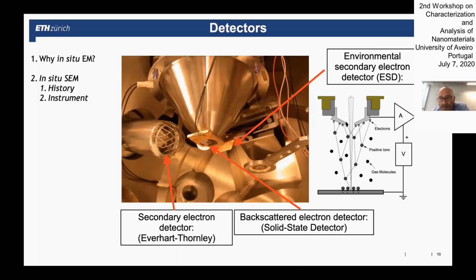And on their way, when they get accelerated towards this anode, they can hit gas molecules that are in the chamber and ionize these gas molecules. And in this process, create more secondary electrons in the gas phase. And they get also accelerated to the positive anode, and eventually even excite more secondary electrons through further interactions with gas molecules. So what you have is that a single secondary electron actually can give rise to an avalanche of secondary electrons. And this is actually a signal amplification. So the electron beam hits the sample somewhere, and you create an avalanche of secondary electrons that you can then detect. It's a bit like a Geiger-Müller counter. Yeah? So you have a nice signal amplification.